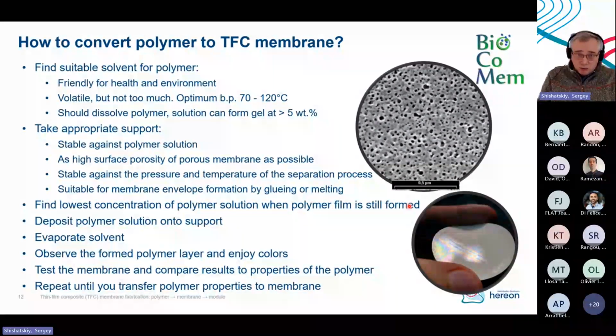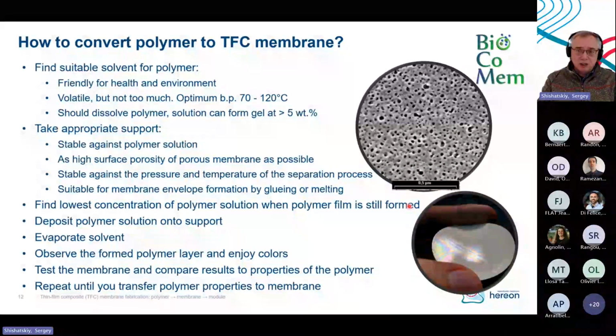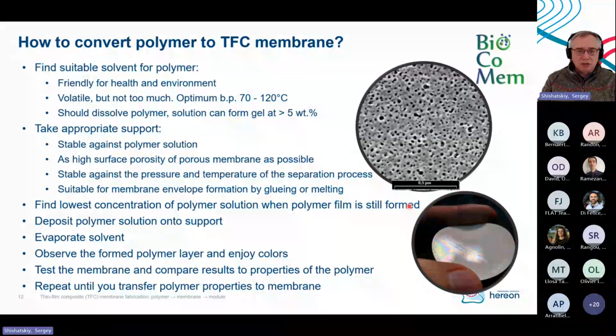The solvent should dissolve the polymer, so it should form a good solution of the polymer. But at a concentration of roughly above 5%, it can go into gelation. Sometimes we use this effect of gelation for the production of very tuned membranes for very specific applications. Then we need to take an appropriate support.